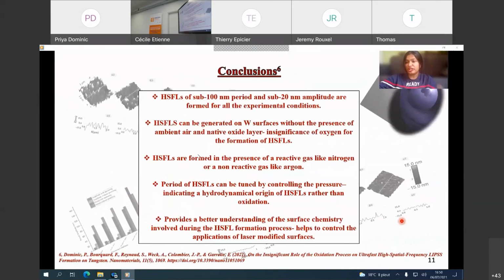So the most important conclusions that we get from this work are that HSFLs of sub 100 nanometer period and sub 20 nanometer amplitude are formed for all the experimental conditions. And HSFLs can be generated on tungsten surfaces without the presence of ambient air and native oxide layer. So that indicates the insignificance of oxygen for the formation of HSFLs. And HSFLs are formed in the presence of a reactive gas like nitrogen or a non-reactive gas like argon. And the period of HSFLs can be tuned by controlling the pressure. So it indicates a hydrodynamic origin of HSFLs rather than an oxidation-based origin.